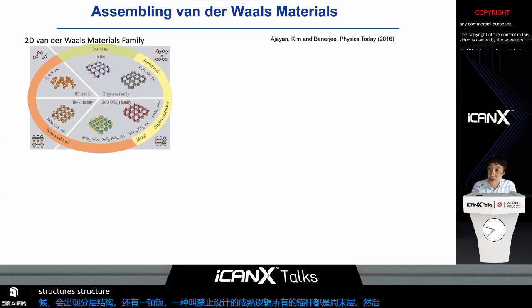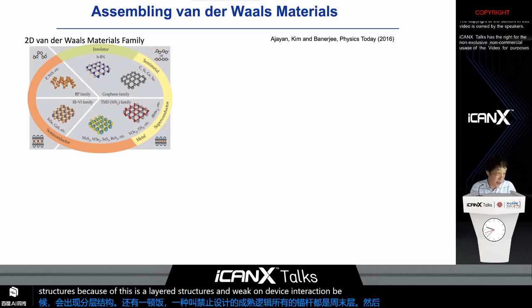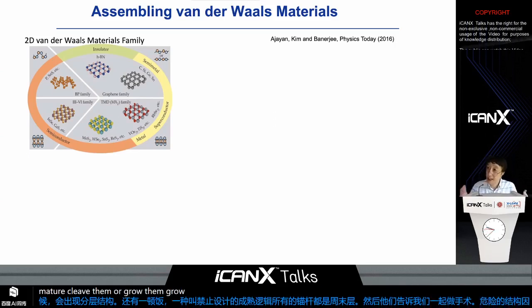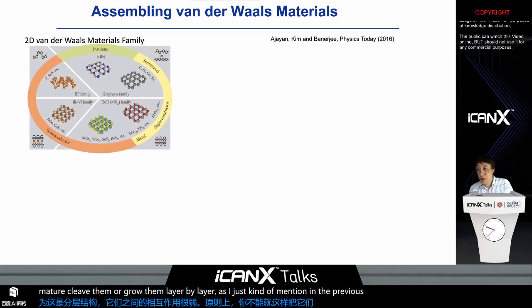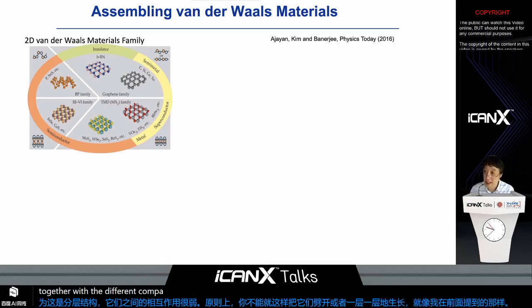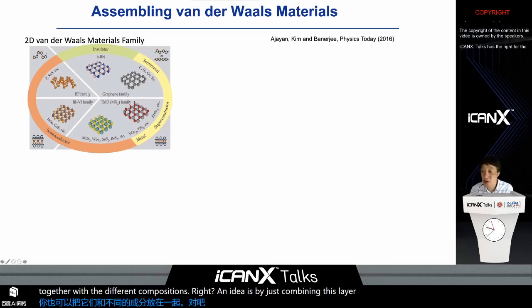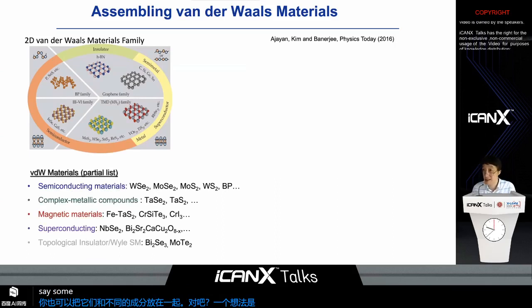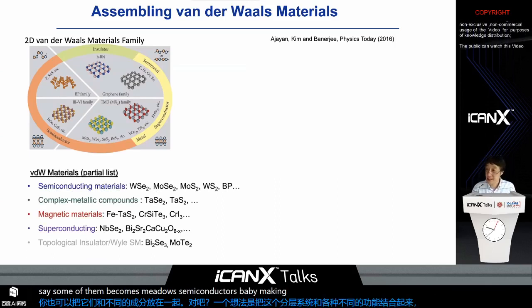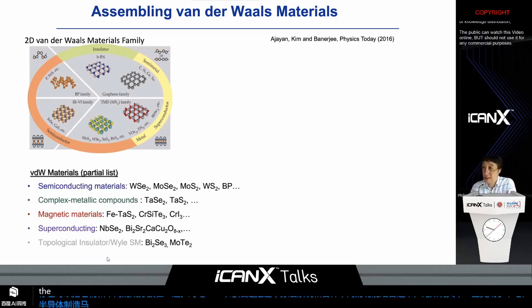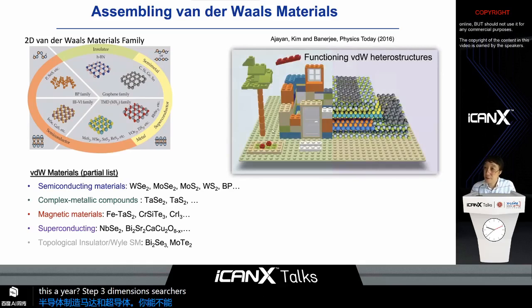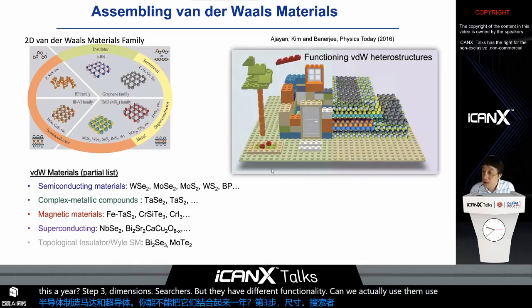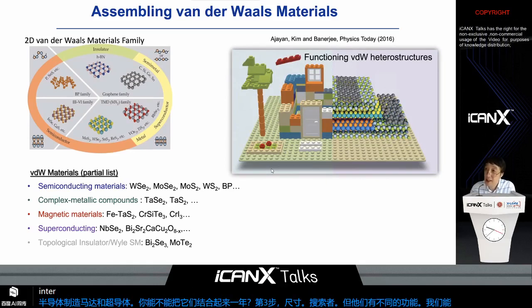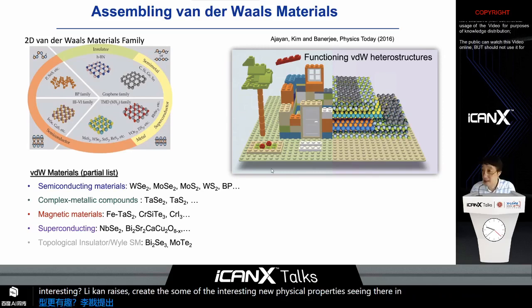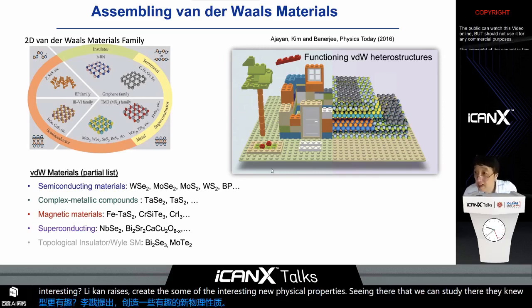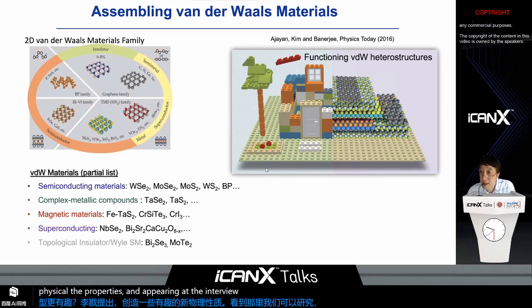Because of these layered structures and the weak van der Waals interaction between them, in principle you can take this material and cleave it, or grow it layer by layer, as I just mentioned in the previous sections. But you can also stack the layers together with different compositions. The idea is to combine layered systems with all sorts of different functionalities, say metals, semiconductors, magnetic materials, and superconductors, into stacked three-dimensional structures with different functionalities. Can we use them for different types of devices? And more interestingly, can we create new physical properties that we can study, appearing at the interface? So that is the basic idea.